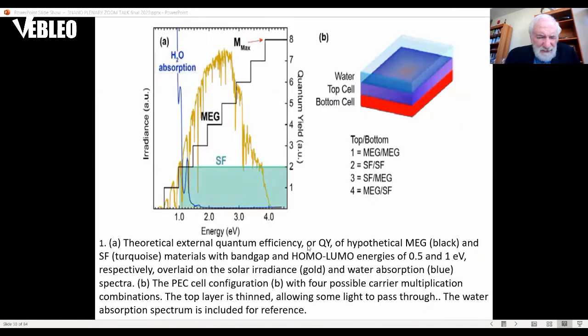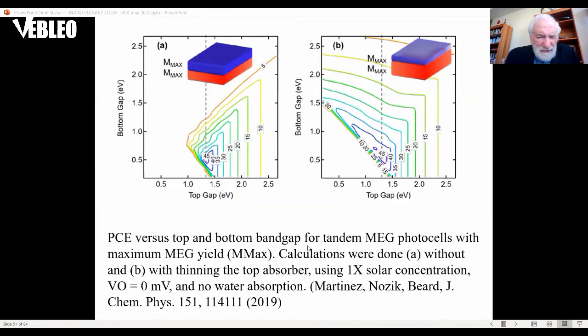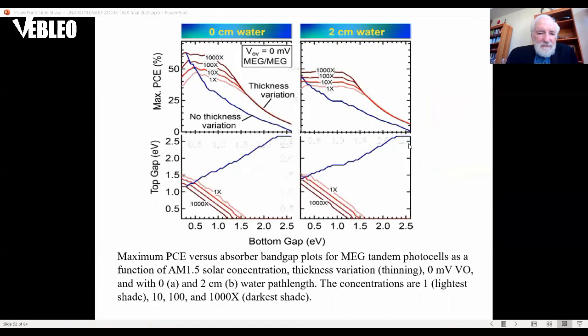So I'm running out of time here, so I'll just end with a new effect, which is when you do fuel production water splitting with 2 layers. If you thin the layer, instead of having them both absorbing the full number of photons that are greater than the band gap of each layer, you allow some of the light that would normally be absorbed in the top layer to leak through. When you compare the case where you don't have thinning to the case where you thin to the optimum thickness to allow some light to operate in both halves, you have an interesting effect where you extend the range of band gaps to give you the high efficiency. So this is summarized here.